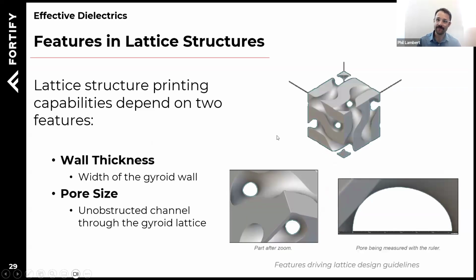So there are some features about this unit cell that are very important to Fortify. The features of this unit cell are the overall size of the unit cell, but also the wall thickness, which is the thickness of these undulating surfaces here, and then the resultant pore size. And so we pay very close attention to the pore size and the wall thickness of our unit cells, because those generate the limits in our effective media. How thick of a wall we can print represents how high of a dielectric constant we can achieve. And how small of a pore we can print and clean represents that same limit.